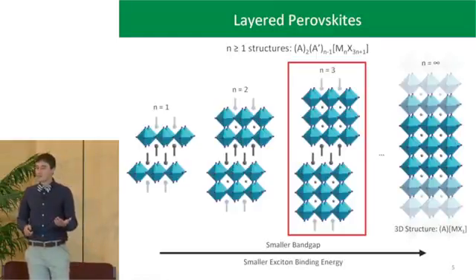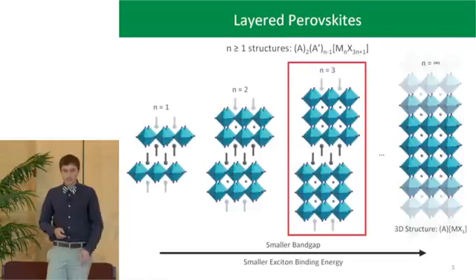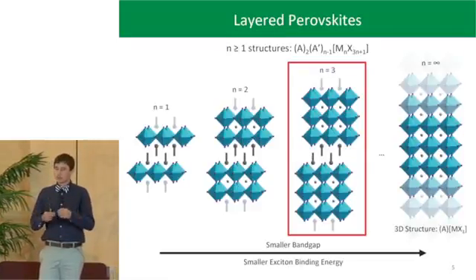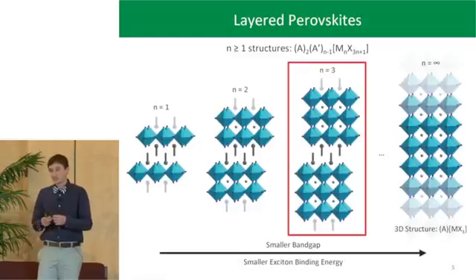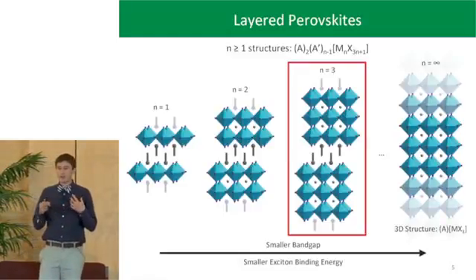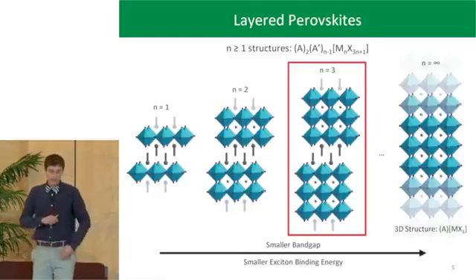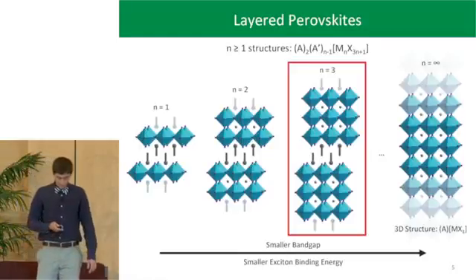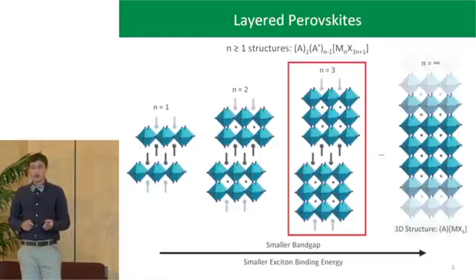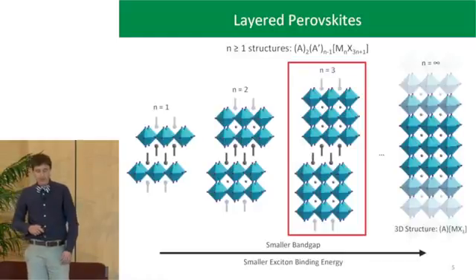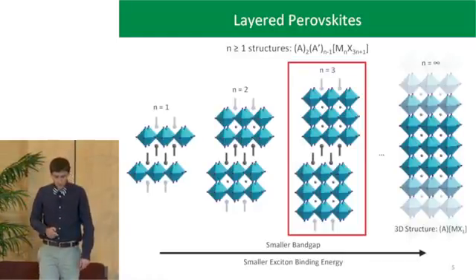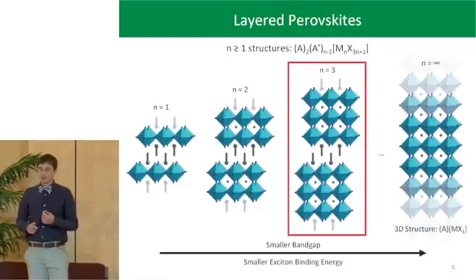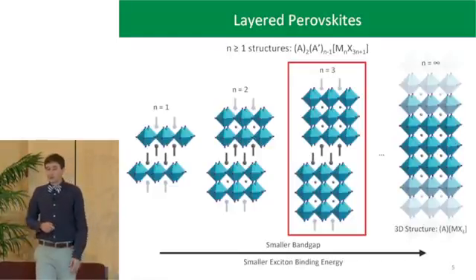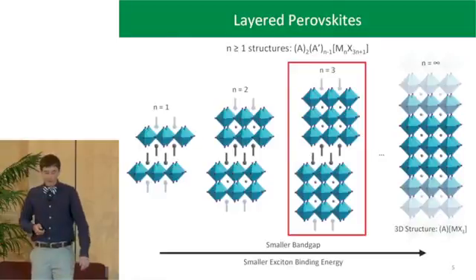And so this here on the left is a very typical example of a layered perovskite. We still call it a perovskite because it's corner-sharing octahedra, in this case of lead iodide octahedra. But because we're adding in larger organic cations, we're separating different layers of that material, so we actually get a layered structure. This, however, is just one of many types of layered perovskites that we like to call the N greater than 1 structures. And so the N value here is essentially counting the number of lead iodide octahedra in each sheet. And so I showed you before the N equals 1. However, the N equals 2 and 3 are shown here as well.